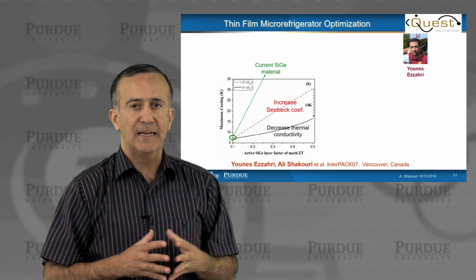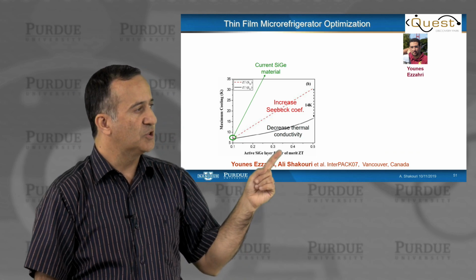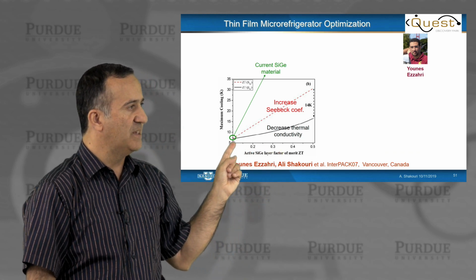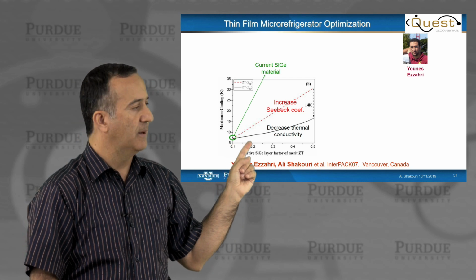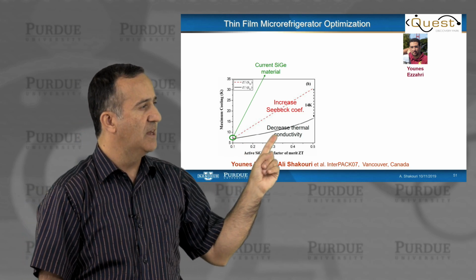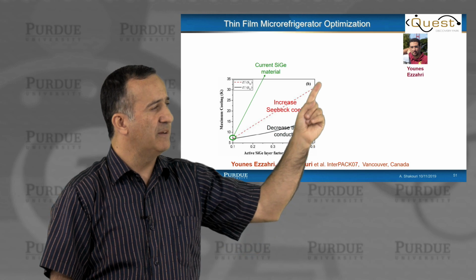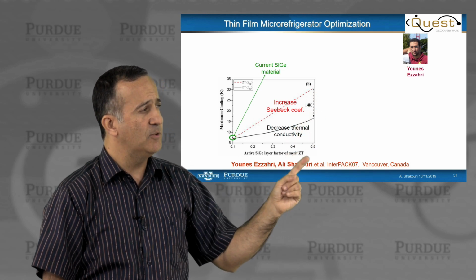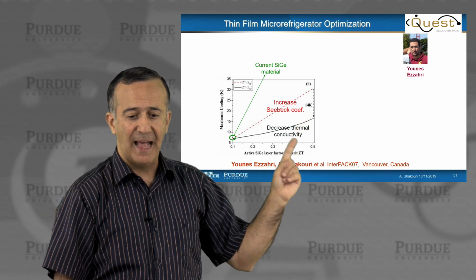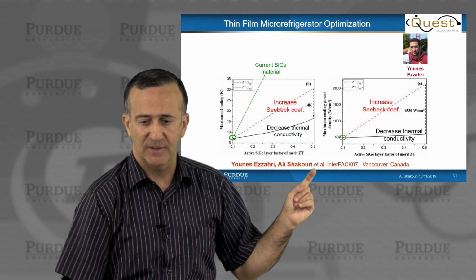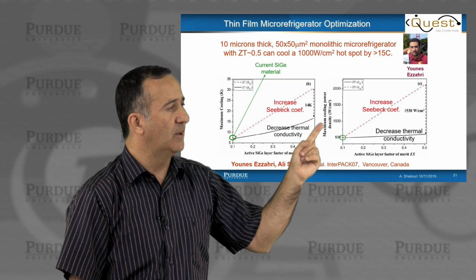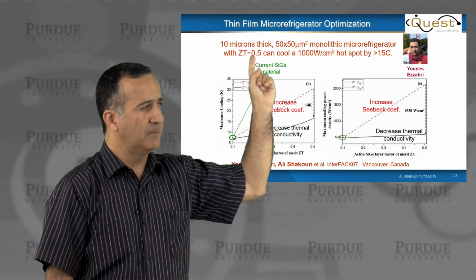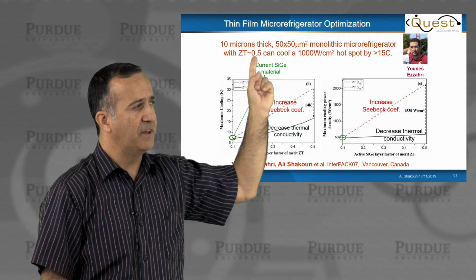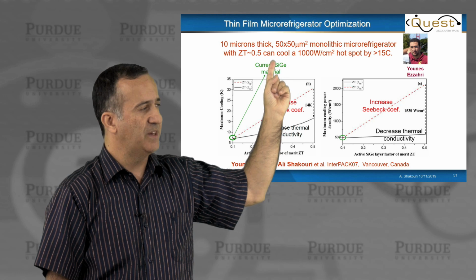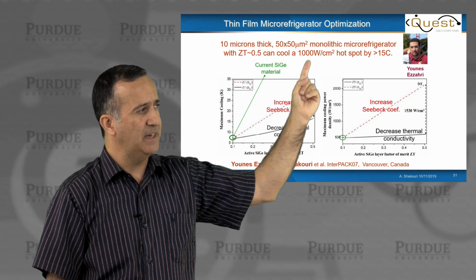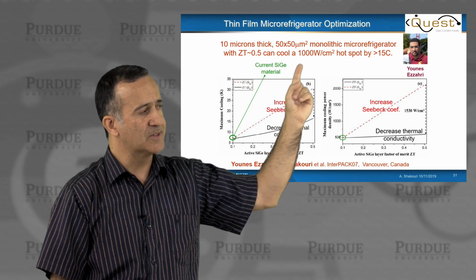Later on in an analysis, we were able to show that you can increase the maximum cooling from the 5 to 7 degrees up to 15 or even 30 degrees if you have a ZT of 0.5 and if the material thickness is about 10 microns. So these are some of the predictions here. 10 micron thick monolithic microrefrigerators with a modest ZT can really achieve kilowatts per centimeter squared.